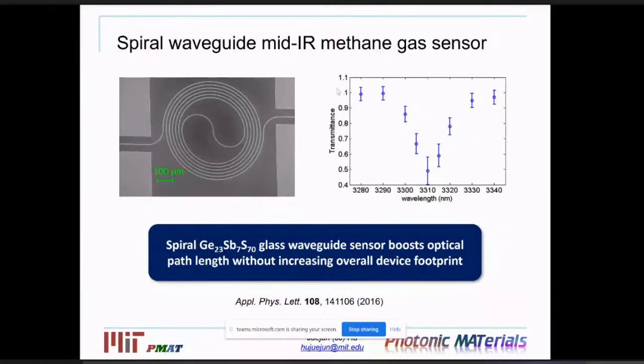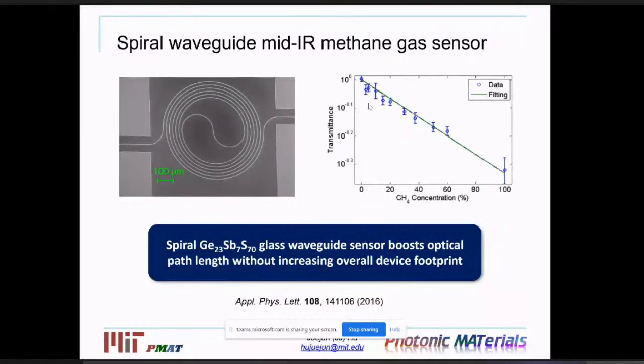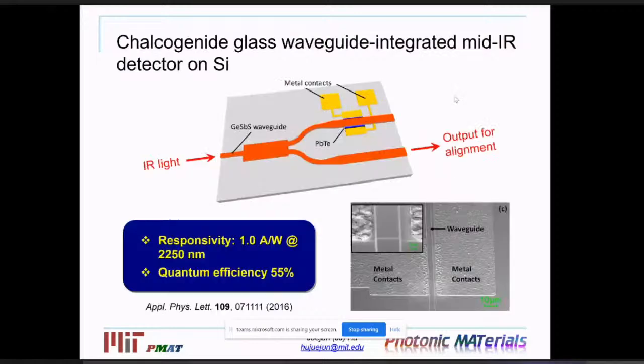On the right-hand side, I'm showing you a measured spectrum using the sensor that clearly shows an absorption peak centered around 3.3 microns, which corresponds to the absorption wavelength of methane molecules. We have also measured the response of the sensor as a function of the concentration of methane, and we get this very nice linear relationship that's in agreement with the classical Lambert-Beer's law. So we can then use this kind of sensor to perform quantitative detection.